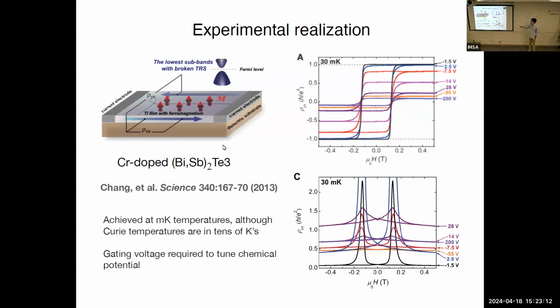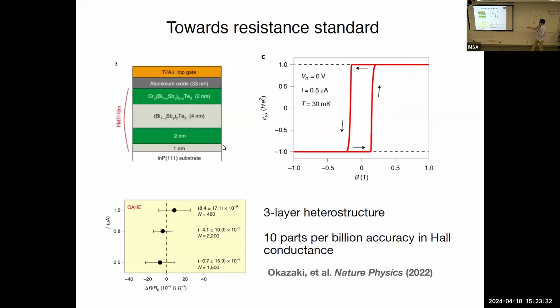The Curie temperature of chromium is almost 100 Kelvin, and we only see this effect up to 30 millikelvin. So people started to think about how to improve it, but another direction in which this field evolved was towards getting very precise resistance measurements.